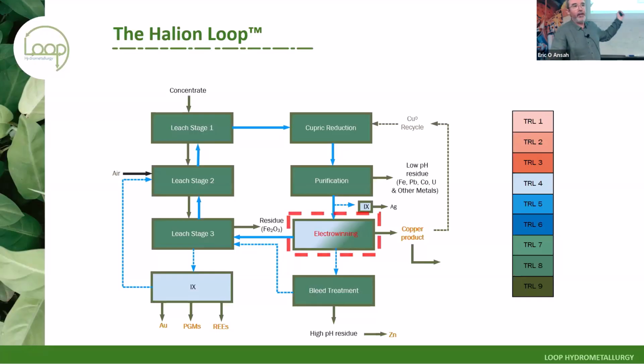Leach stage 2 is where the guts of the reaction happen. You've got your mineral reacting with cupric to form cuprous. You've got your cuprous reacting with air to reform cupric, and it just churns through the mineral. We go in a countercurrent, so we've got a thickener, and the clear overflow passes up to leach stage 1, where it's exactly the same reaction, but without the addition of air.